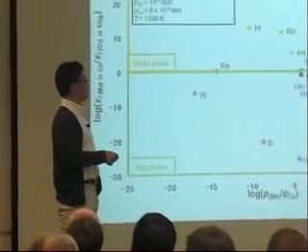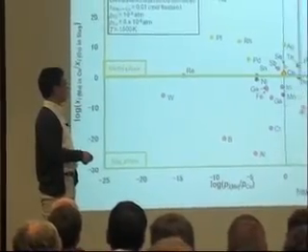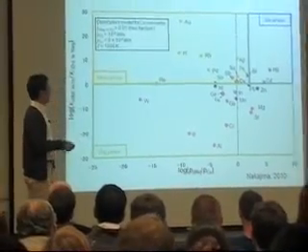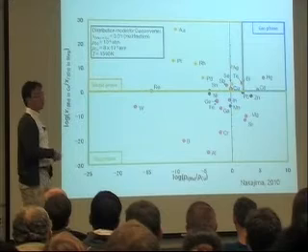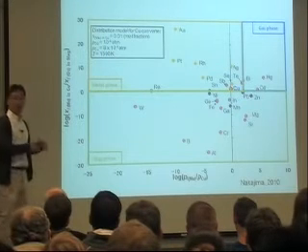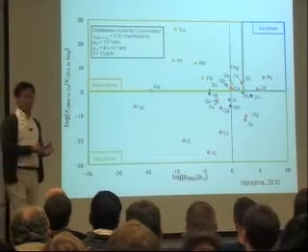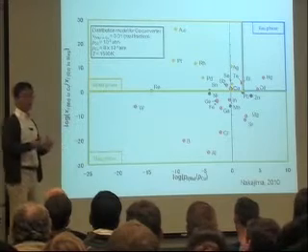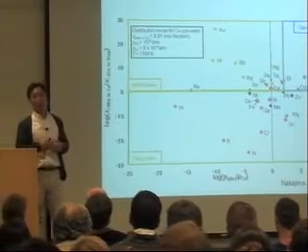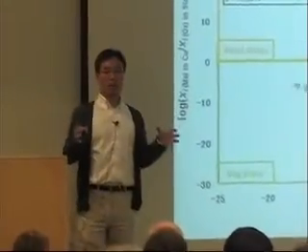The problem is that many of those materials that are in question here, gallium, germanium, boron, tungsten, magnesium, zinc, will be separated as part of slag. Once it is put into slag, it's very difficult to separate from there. So the traditional smelter approach is not really working very well for those rare earth elements. Not only because of this thermodynamic limit, but also because the amount of those metals in the product is so limited, it's very small. So separating them does not really make economic sense.